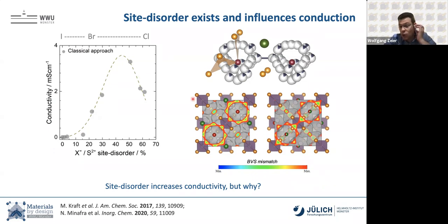Why is that the case? We already see it if we calculate so-called bond valence sum maps. It's pretty much a fancy word for: is there enough space for ions to jump around? So if the structure is fully ordered, you see these heat maps where lithium is just rotating around the cages.